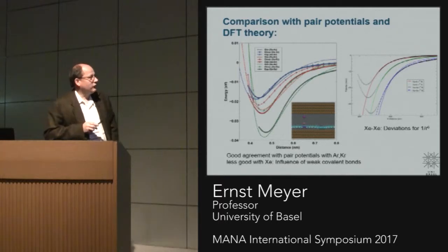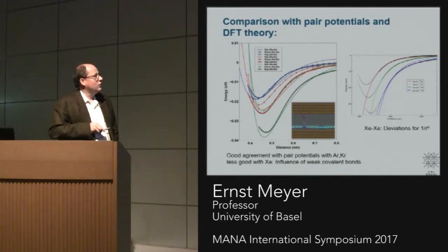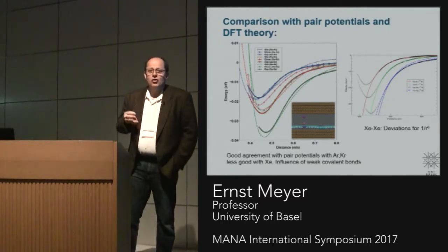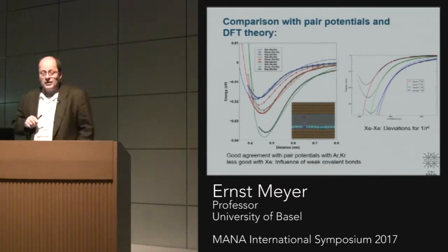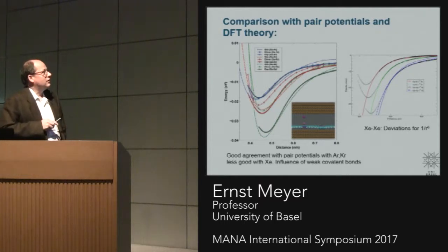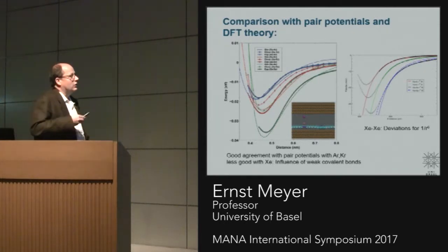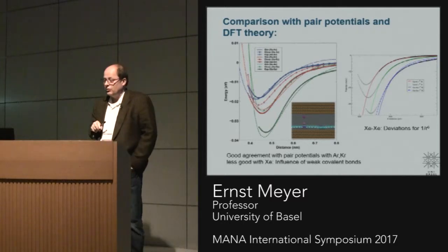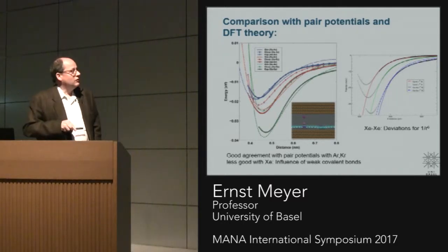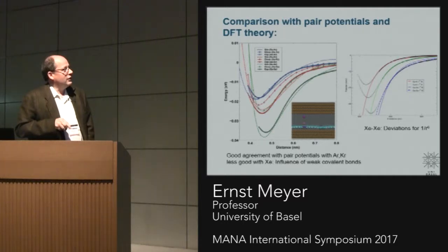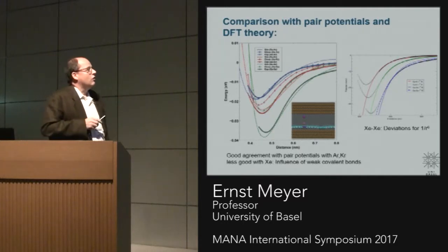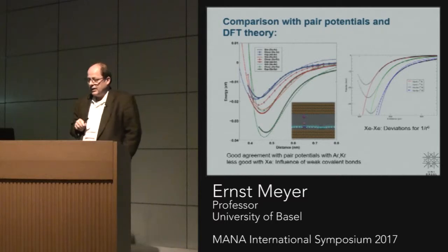And yeah, there were some surprises. For argon and krypton, it's more or less what you would expect from the normal pair potentials we have available from gases. But for xenon, there is really a big difference. So this is the experiment, and this other line is the one we get from the pair potential. So there seems to be quite some deviation. Even the R to the 6 doesn't follow very well for xenon. So xenon already shows quite some deviations.